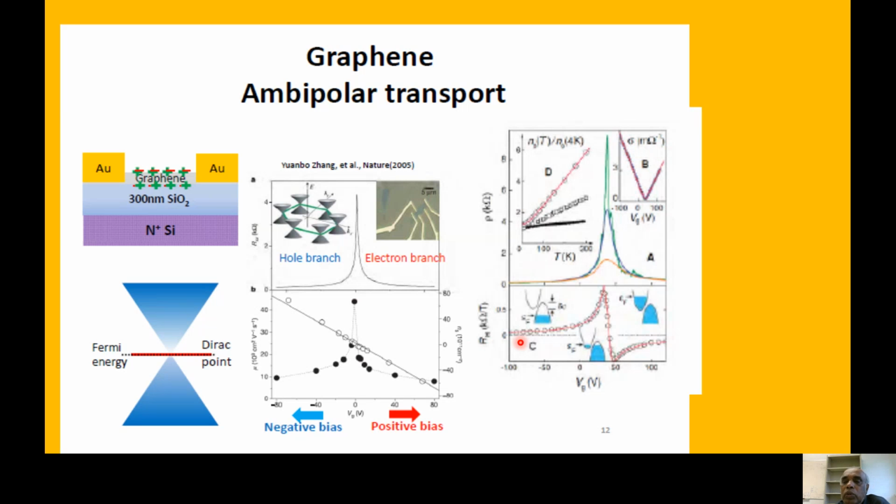Then this again shows similar behavior for different temperatures. This one shows the Hall coefficient. Like I said, the Hall coefficient is a measure of your charge carrier type, right? You can see here your Hall coefficient is positive, and this is 0. So that means your Fermi energy is in the valence band, right? Now if I go from here by doping this way, it goes to 0, becoming exactly 0 here. Then when it moves to the conduction band, you can see it comes to negative and stays negative. That means your Fermi energy is now in this direction.